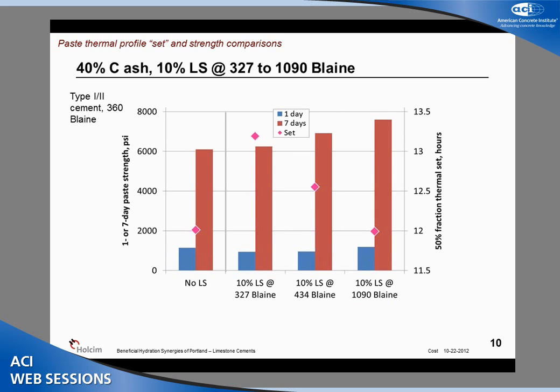Now, the interesting thing is what happens when you do this same work with SCM replacements as we would use in concrete. Here is the same comparisons for a 40% replacement using a Class C fly ash, which is a high calcium Class C ash that contains a fairly significant aluminate contribution. And this type of fly ash results in significant retardation anyway. The numbers on the time scale for setting are different here, the much longer setting times. And as you go to the coarse limestone replacement at 10% of cement, then you begin to see even more retardation. But that retardation is mitigated as you go to the finer limestones.